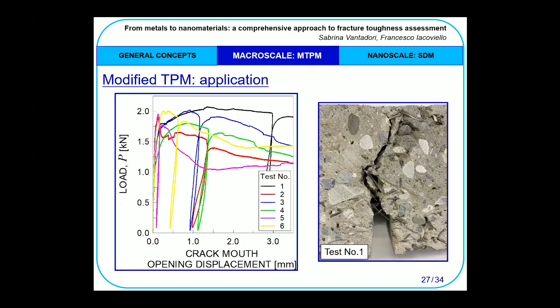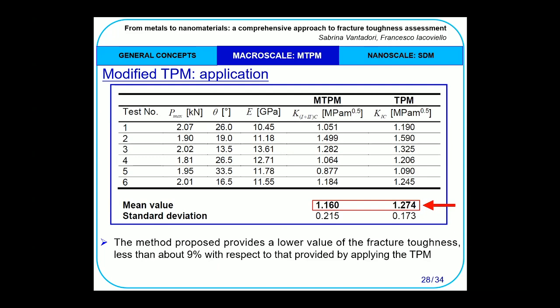Also, a typical crack path is reported on the right-hand side. In this table are summarized the results obtained. The average value of the fracture toughness computed by applying the modified two-parameter model is equal to 1.16 megapascal square root meter. The corresponding value obtained by applying the original method, that is the two-parameter model, is equal to 1.274 megapascal square root meter. Therefore, the method proposed provides a lower value of the fracture toughness, less than about 9%, with respect to that provided by applying the two-parameter model, which can be regarded as a conservative result.